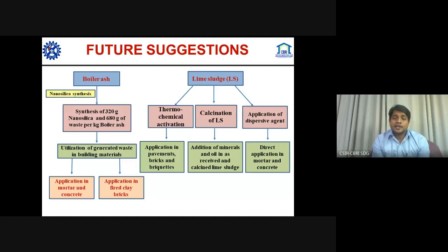And for the lime sludge, there is a possibility of thermochemical activation, calcination of lime sludge, and application of dispersive agents. The thermochemically activated lime sludge can be directly used for pavements and for the production of bricks and briquettes, while the calcined lime sludge we can use with other minerals and oil, along with as-received lime sludge. With the dispersive agent, direct application in mortar and concrete is possible.